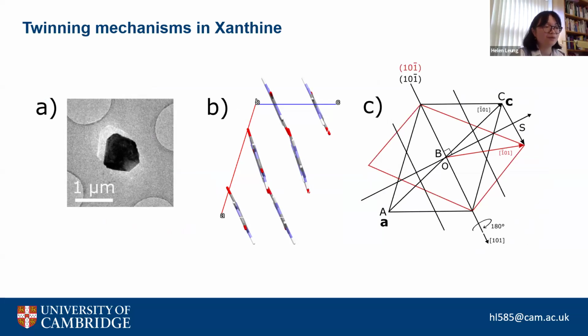We found that we essentially had twins in xanthine where the composition plane, in twinning notation the plane that doesn't change, was the plane of the hydrogen bonded layers. So the layers of molecules that you can see clearly were not changing, and we were not breaking bonding within them. But by rotating or reflecting about the 101 direction, which is pointed out in C, that is basically our twin boundary. Rotating across that twins the xanthine crystal, keeping those hydrogen planes, the 10 bar 1 planes in this example, consistent with each other.